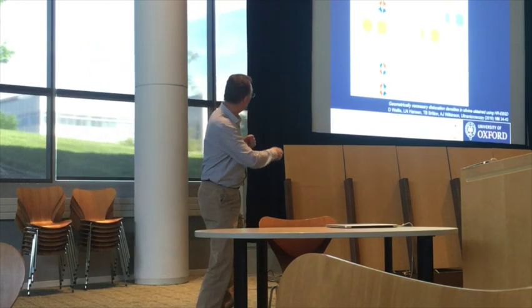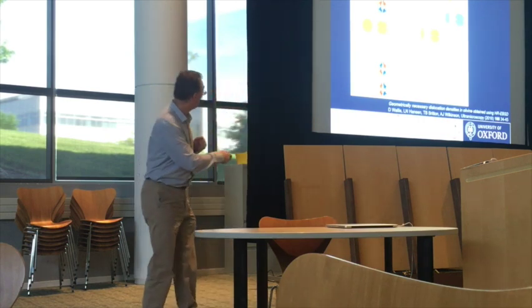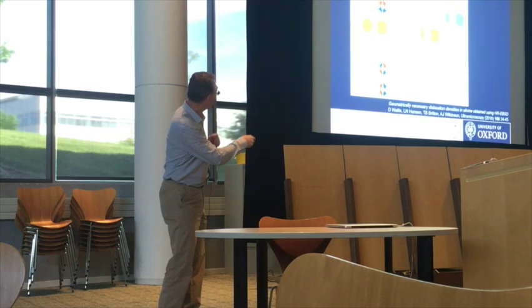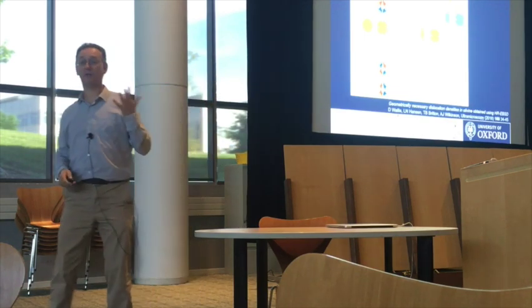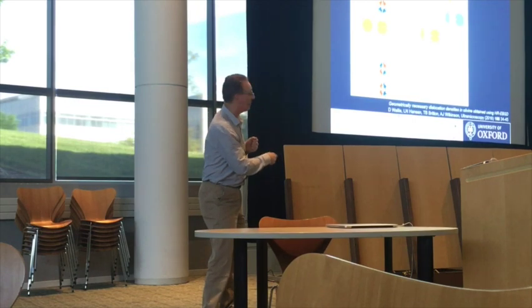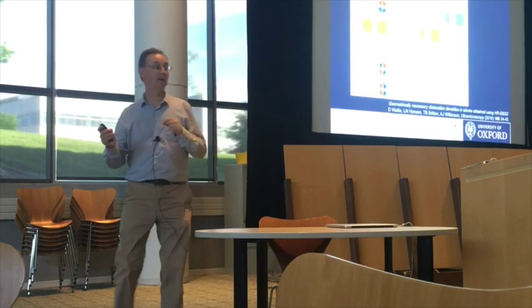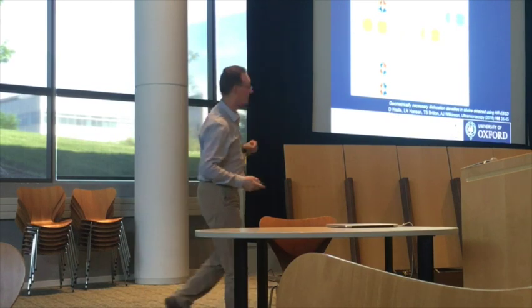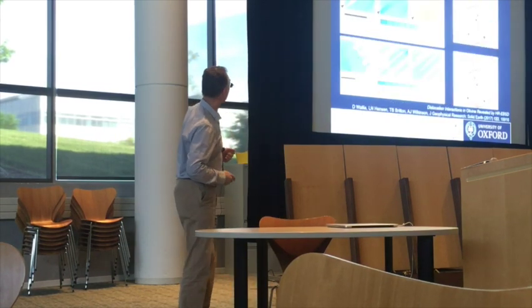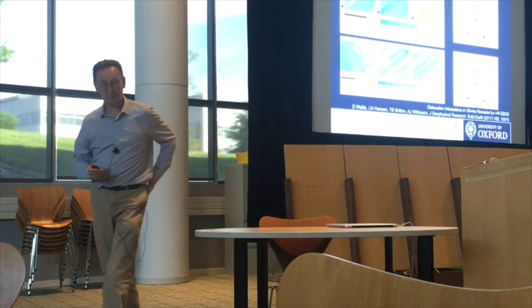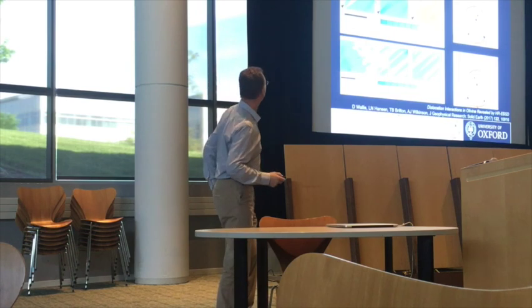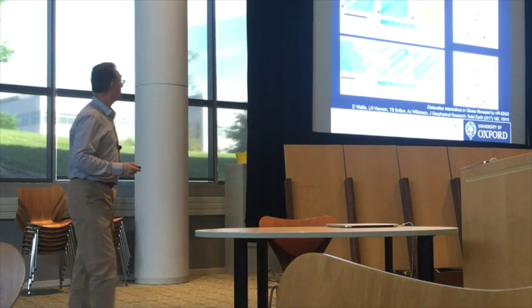The columns in here are different ways of trying to recover that, and the best one, hopefully you can pick out, is this one in here, which is using a pseudo-inverse and our 6 constraints. Effectively it works really well, apart from a couple of blind spots in here where, as I say, we're not going to measure the curvatures that those dislocations would generate. So we have to be armed with a little bit of forethought just in case we end up falling down. But here are some examples looking at olivine.